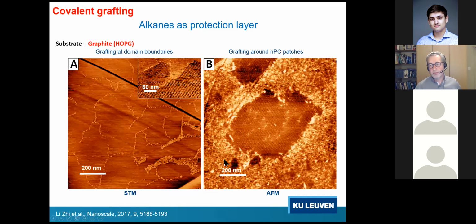But it's not perfect. And why is it not perfect? Well, these areas are graft free, but these bright areas are areas where you have grafted molecules, and they follow this kind of lines. Why this kind of lines? This is because these alkane molecules form polycrystalline domains on the surface. At the boundary between two of these alkane 2D crystals, you have a defect, basically, because there is not perfect coverage of the substrate. And in those defects, the radicals can attack.